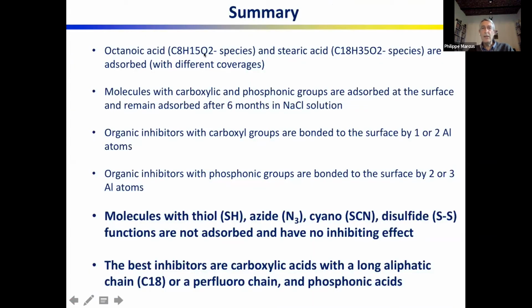So just to summarize, and because time is running, let's move directly to the two conclusions here. The molecules with thiol, azide, cyano, and disulfide function are not adsorbed, and as a consequence, they have no inhibiting effect. The best inhibitors are the carboxylic acids with a long aliphatic chain, and the perfluoro chain, and also phosphonic acids. So this systematic study allowed us to select the best corrosion inhibitors.